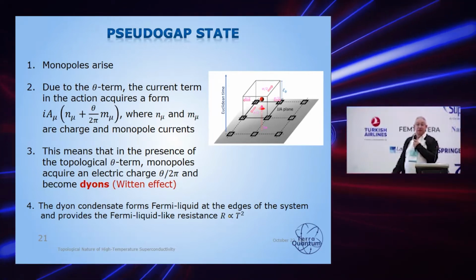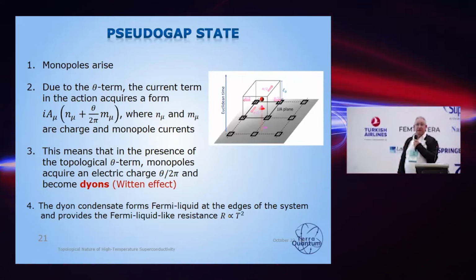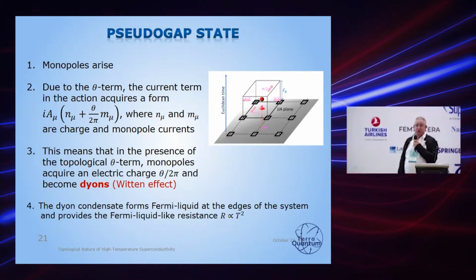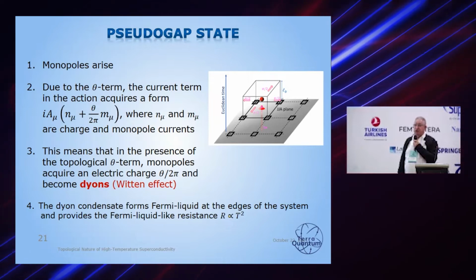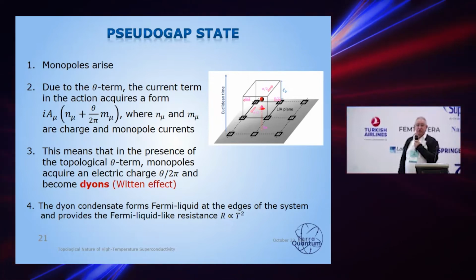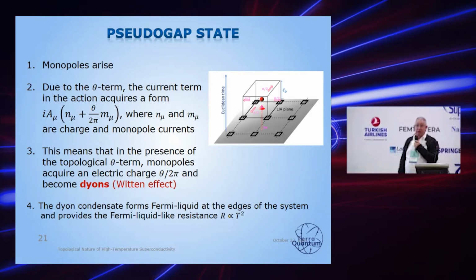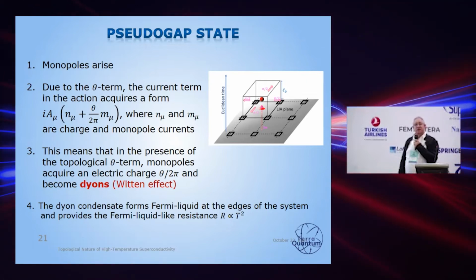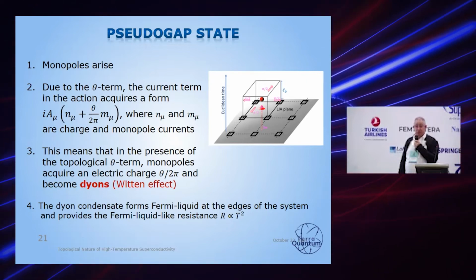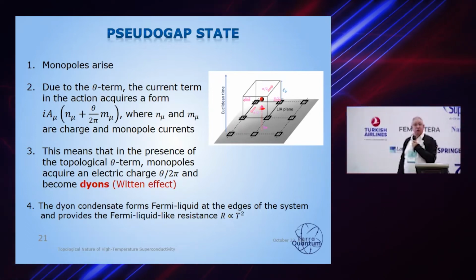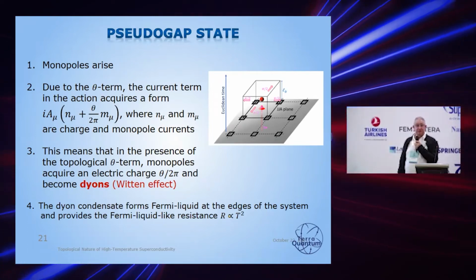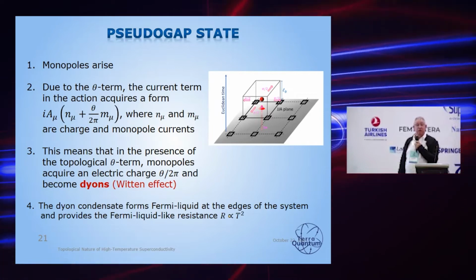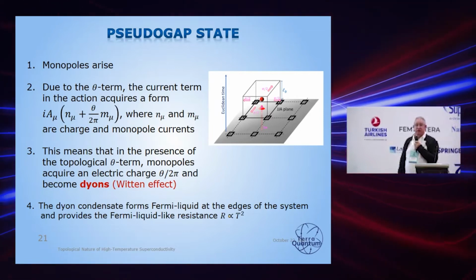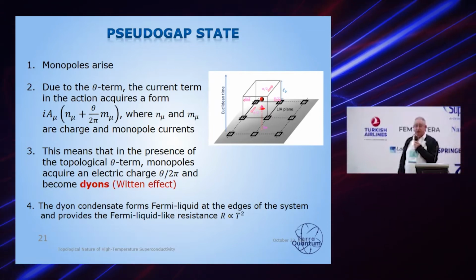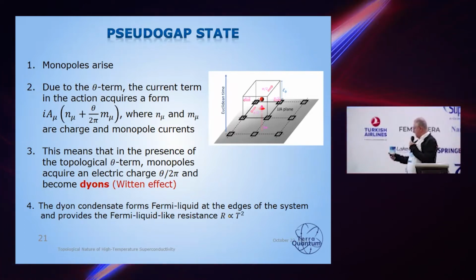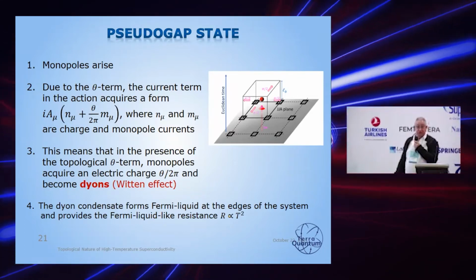Because this phase near the superconductor-insulator transition should have a granular structure, then we should have surface or bound states, topologically protected. Dyons at the boundaries of these bubbles acquire fermionic statistics, so they form a Fermi liquid. And since they're topologically protected, they behave exactly like a Fermi liquid. And this is exactly where this T-squared term appears from.